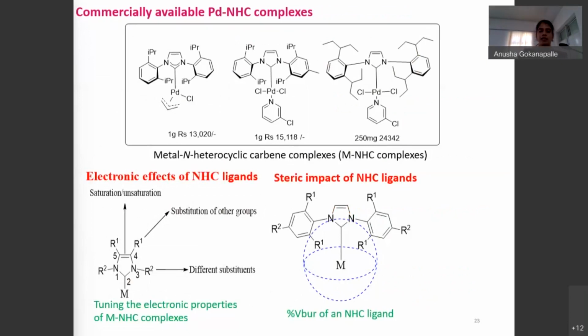Electronic effect on NHC ligand. Substituents at C4 and C5 positions may not have much impact on the electronic properties of NHC, but variable N substituents would tune the electronic properties of metal NHCs. This is the steric impact of NHCs. Nolan and Cavallo in 2010 brought a concept of percentage buried volume, which suggests the fraction of the volume of a sphere centered on the metal that could be occupied by the NHC ligand, and also identified the correlation between percentage buried volume and experimental bond dissociation energy.